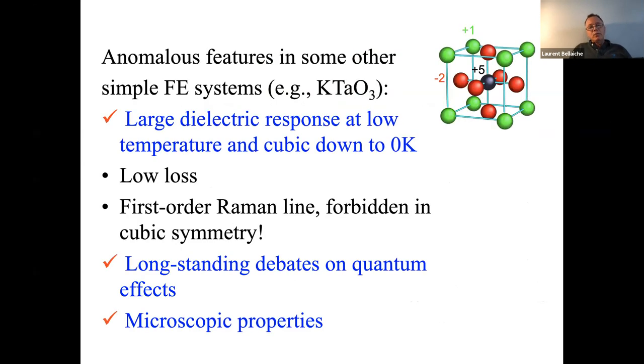And then we decided with Alireza Akbarzadeh to do something else. For instance, we look at potassium tantalate. There, this is a very interesting system. It has a huge dielectric response at low temperature, but it's still cubic down to zero Kelvin. And there are very strange things like a first-order Raman line, which is forbidden in cubic symmetry. So people have debated what's going on inside this system, and they say it's quantum effects. If there were no zero-point vibration, it would be ferroelectric. There is zero-point vibration, and it kills ferroelectricity. So this is what we wanted to check.